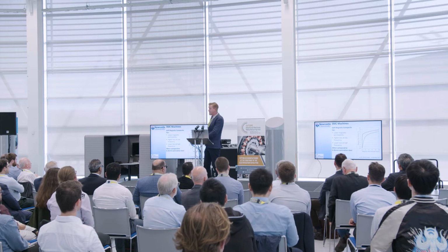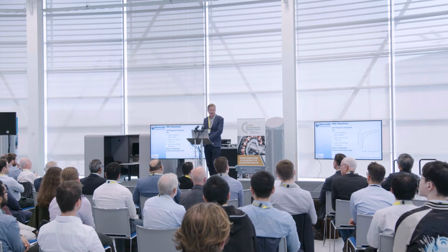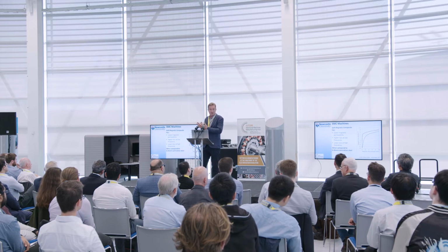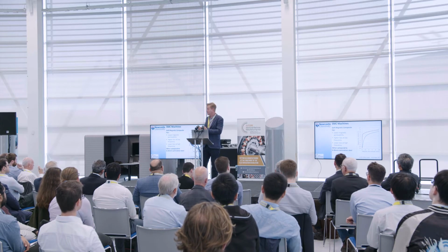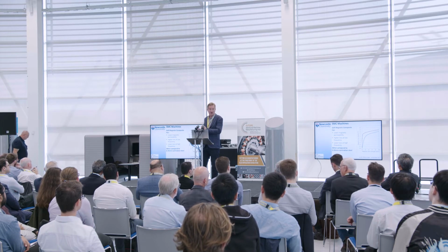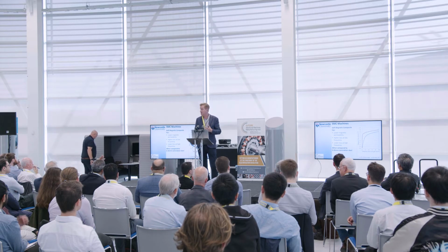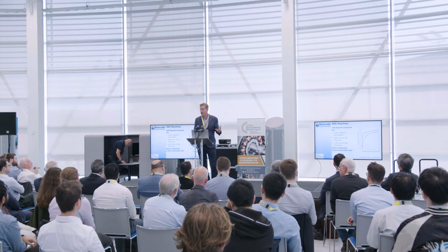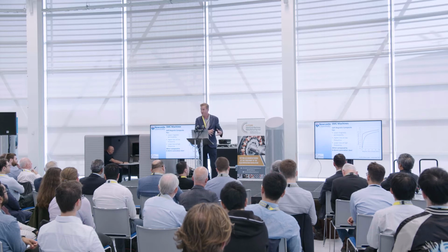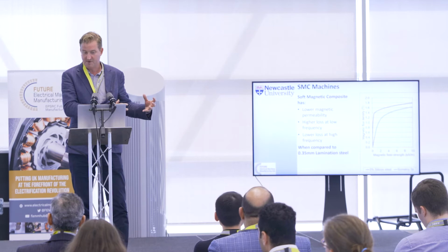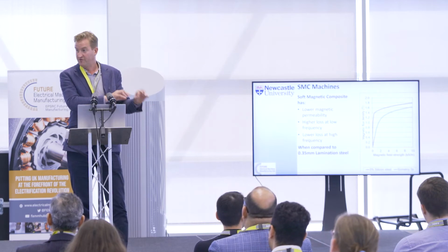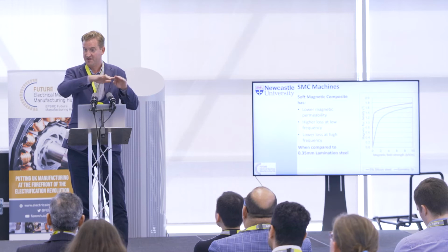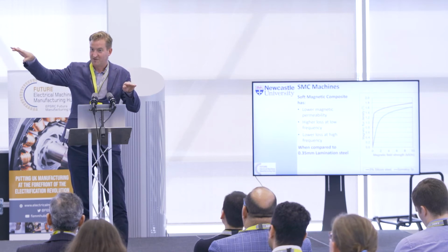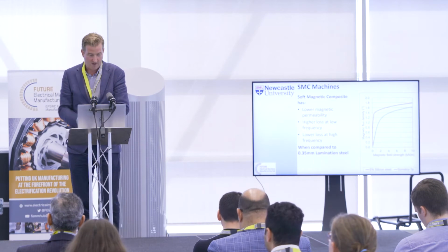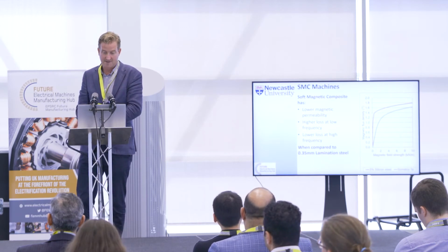A little bit on the design of the electrical machine using soft magnetic composites. The powder has a lower magnetic permeability than solid iron. It has higher loss at low frequency. The hysteresis factor is much higher, so at low speed, low frequency, the iron loss is dominated by hysteresis. The eddy current loss is very low, and at the higher frequencies the hysteresis isn't rising as fast as the eddy currents, and we have lower loss at high frequencies, so there's a balance to be had in there.